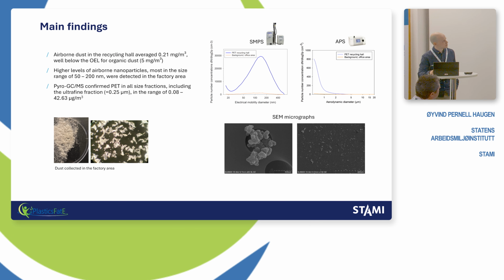So the main findings: airborne dust inside the recycling hall was very low, 0.21 milligram per cubic meter. This is well below the occupational exposure limit for organic dust. We don't have an exposure limit for plastic at the moment.